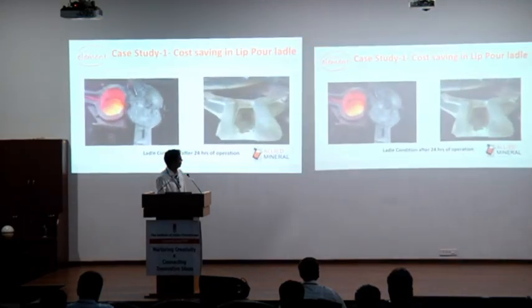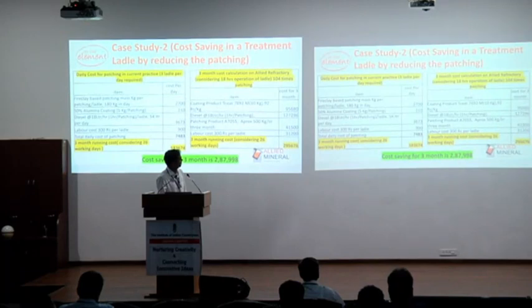This is after 24 hours of operation. Still the ladle looks clean, and it's very easy to clean actually with the help of coating materials. So this is a case study of what we did in a treatment ladle, again by reducing the number of patchings. We were able to show them a cost saving of almost 3 lakhs for 3 months.